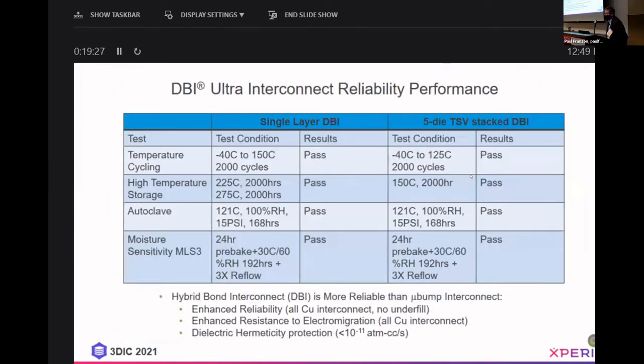This shows our reliability testing and results. We've done basically temperature cycling, high temperature storage, autoclave, HAST type test, and moisture sensitivity test. And both the single layer parts and the 5-die stack parts have passed all of the tests that we put these through.